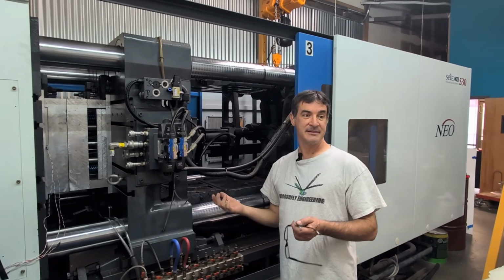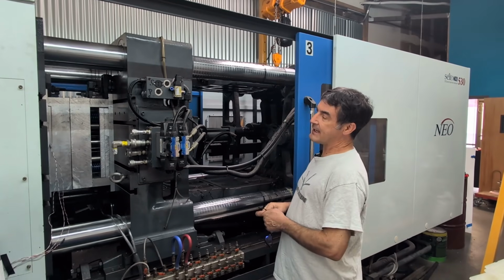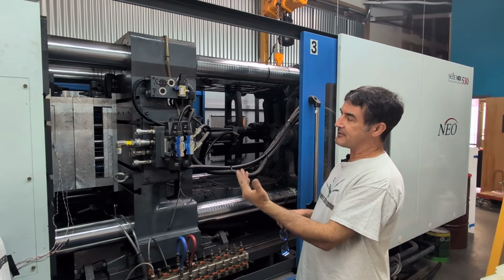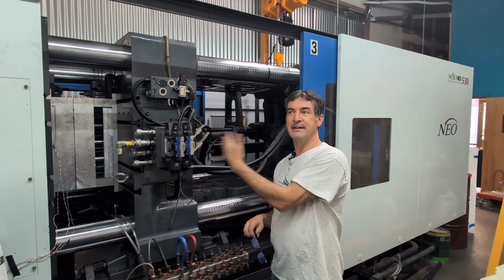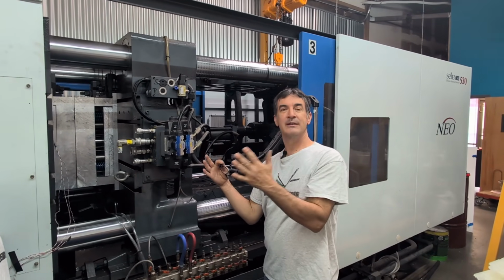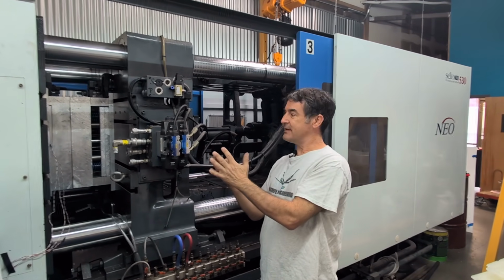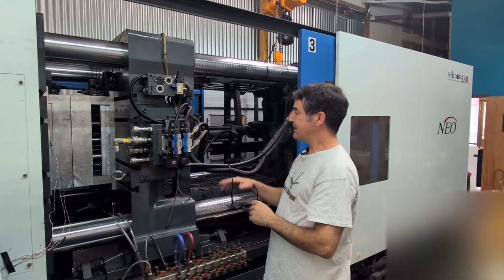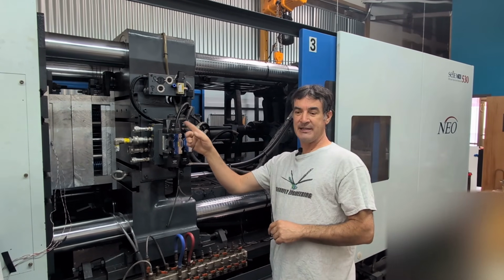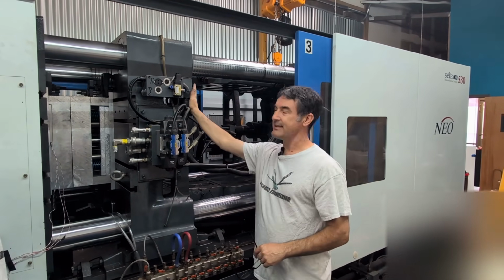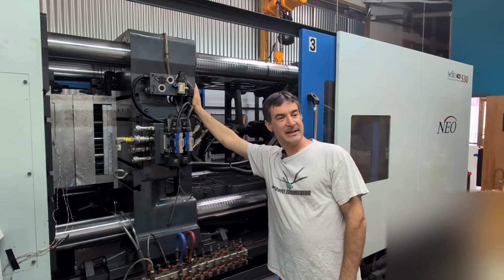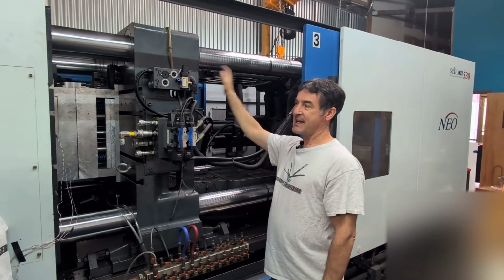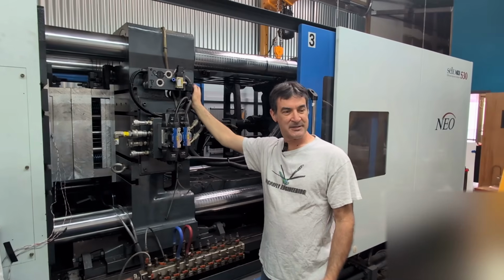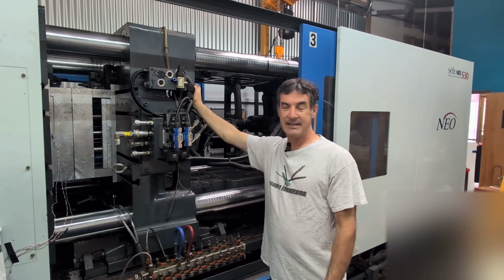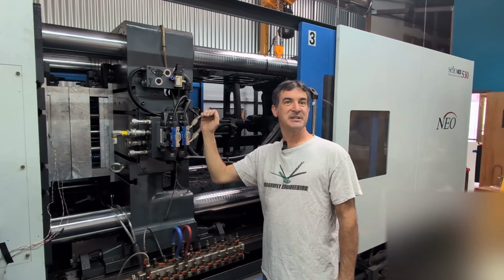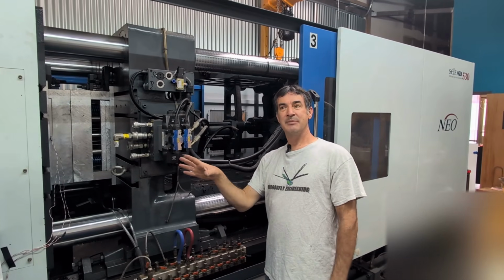It can be up to 10,000 pounds per square inch, and that is where you have to balance the force of the plastic trying to push the mold open from just the hydraulic force of filling out your mold cavity. That amount of force created by the injected plastic needs to be less than the holding force of your clamp. So you size your molding machine to the size of the part that you're going to mold. Bigger parts need a bigger force to keep the mold shut while you're injecting plastic into your mold.